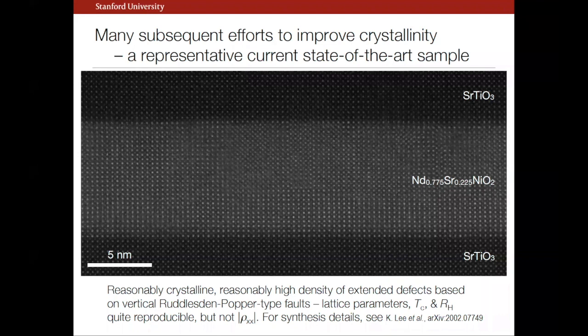Working very hard to improve the crystallinity, and so I wanted to give you a kind of representative state-of-the-art sample. So again, we're limited to about 10 nanometers. You can see if you look over here, it looks pretty nice actually. So in some ways, we're rather proud of this. Right? But also, to be fair, there's a fairly high density of extended defects.